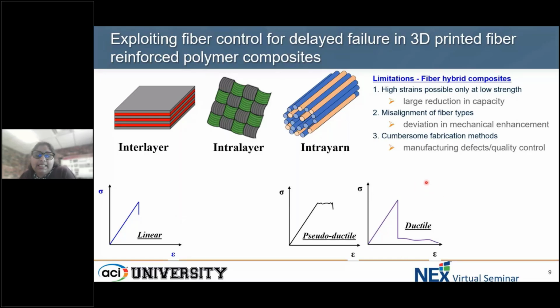The second limitation that was primarily pointed out is misalignment of fiber types. There is not necessarily a controlled way to align these fibers, and therefore those misalignments can cause deviation in mechanical enhancements. So even though enhancements are seen, there can be very high deviations because there's not a controlled way. Of course, intermingling and intermixing these fibers is not at all an easy task. It's highly challenging and cumbersome in terms of fabrication. And this in turn results in manufacturing defects, quality control issues, and again goes back to the mechanical deviations that are seen.